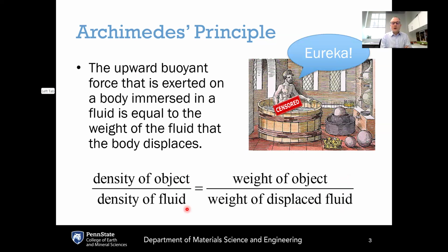The things to watch out for are, first of all, as I mentioned, reactivity between the glass sample and the fluid. And second is make sure that you've got a good quality sample without any inclusions or blisters in the sample. Because if you have any gas bubbles in your glass, those bubbles are going to have much lower density compared to the glass itself, and they're going to give you artificially low values of density. And so it's important to have a good homogeneous glass sample without any types of defects in it that could affect the density.